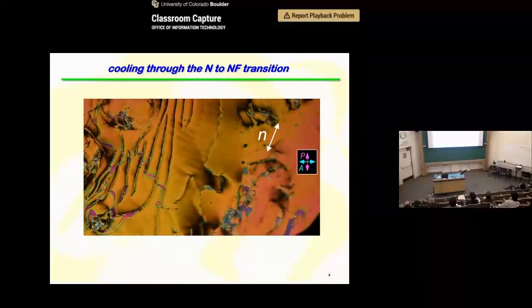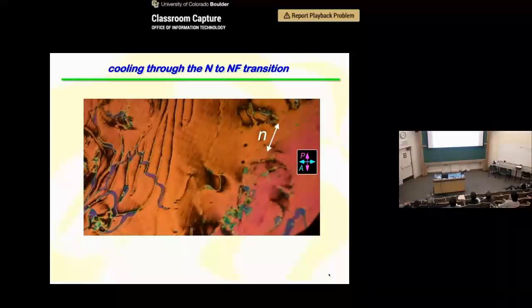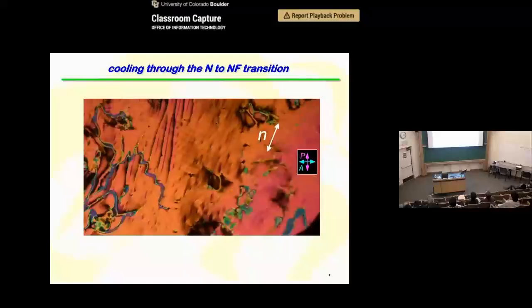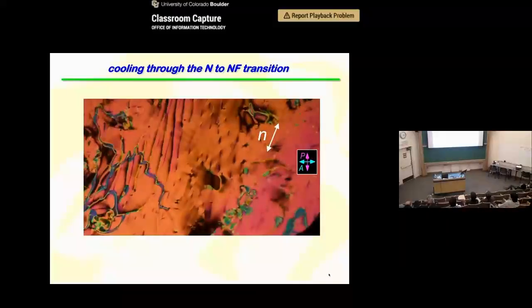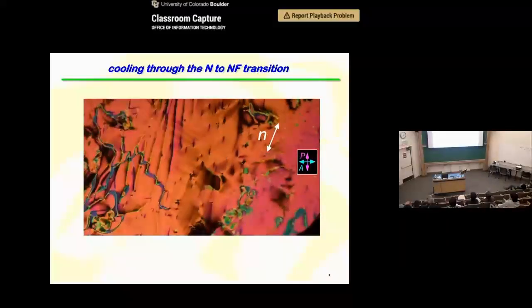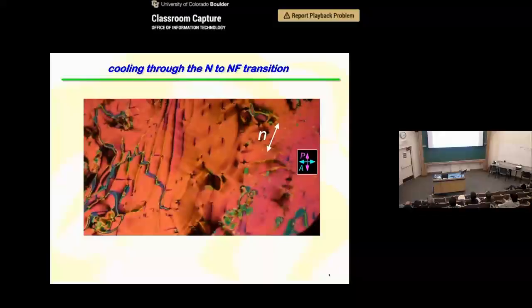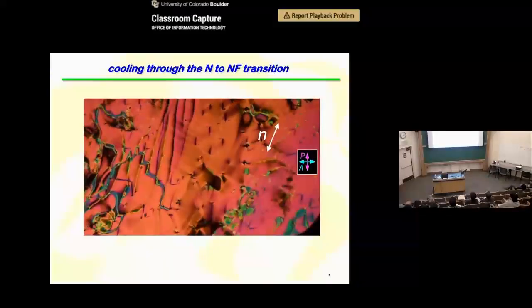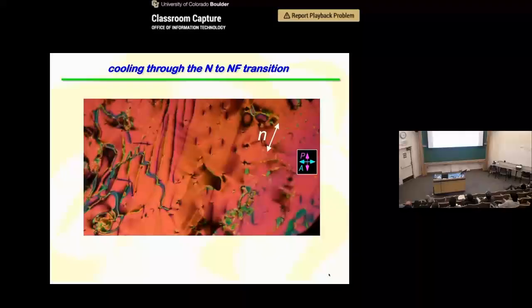Okay. So we're looking at the nematic to ferroelectric nematic phase transition. In a test cell, so the liquid crystal is in between glass plates spaced by like 10 microns. And we're looking in transmission between a cross polarizer and analyzer.